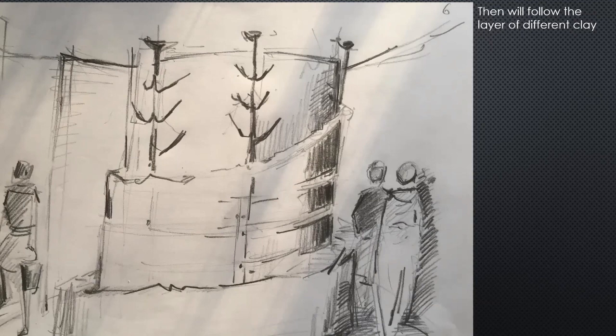The workshop of Phidias was treading a well-known path up to that point, yet the colossal size of the cast asked for new considerations and technical solutions, as the pressure of the mass of the layers of the core on the wax and the casting molds was enormous. Despite the stone ashlars in the center, the molds were reinforced with horizontal iron bands on the outside, which were fastened with